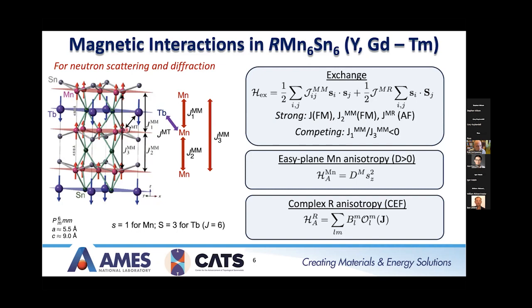And then we have these manganese bilayers also, where there's no rare earth in between them, and we call this J2MM. And then it turns out you also need this interaction between the rare earth and the manganese, of course. But then it also turns out that this J3 interaction, which goes across all these layers I'm showing here, is very important in that it competes with J1.